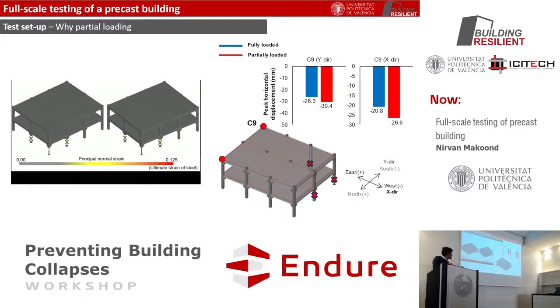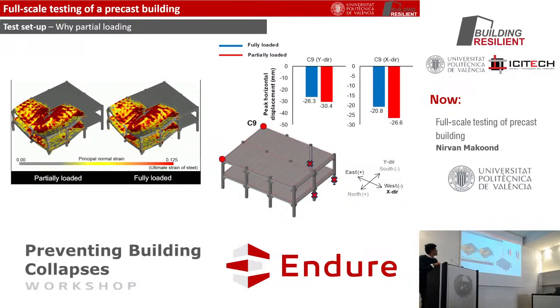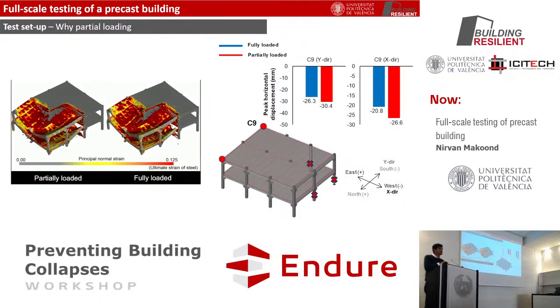And we loaded the structure only partially, because we performed several simulations to compare what we could expect the difference to be between partial loading and fully loading the structure. Expected to be quite similar. However, in the case of partial loading, the drifts in the part of the structure we expected to remain upright were larger, and there was a greater unbalanced moment being transferred to that part of the structure because the columns had a lower level of compression also. So this case was more critical for the upright part of the structure, and therefore it was of interest for us to test, and that it could resist the pulling forces as we expected.